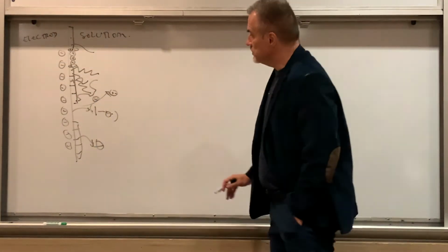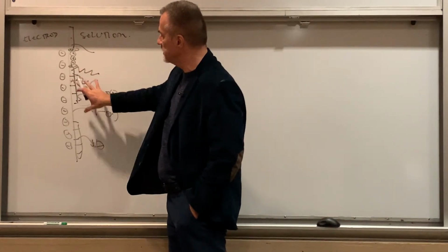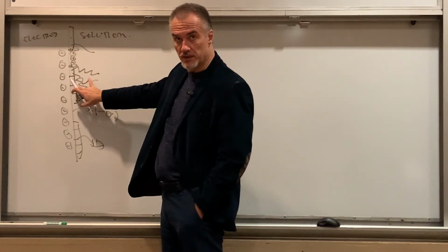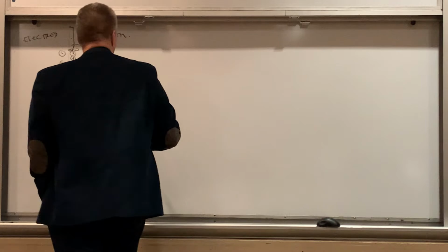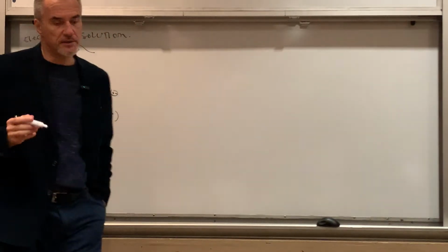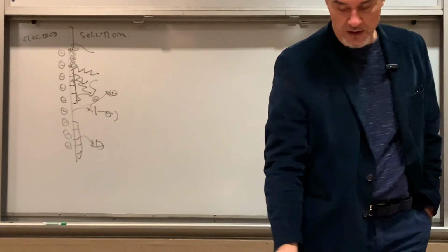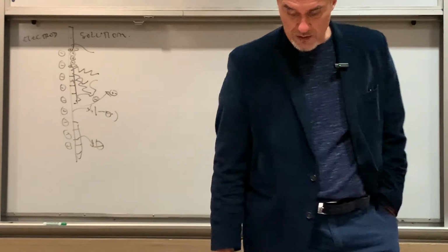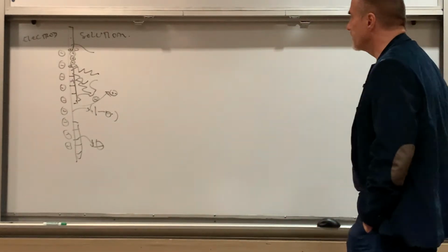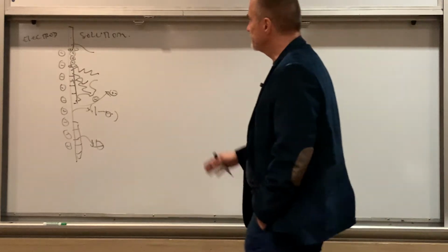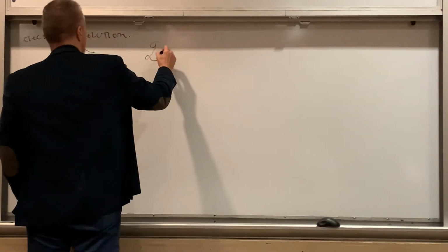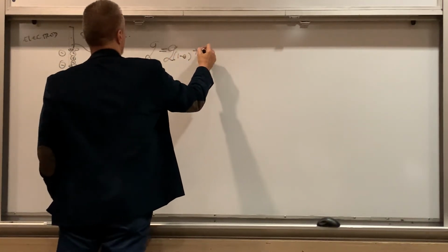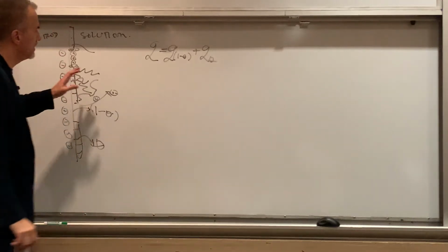Now, if I just look at this specific part here, I can see that there's a different charge here and a different charge here, right? But if I want to calculate the overall charge of the surface, I can say that my charge of the surface Q is equal to Q0 times (1 minus theta) plus Q_A times theta, and this is per surface area.